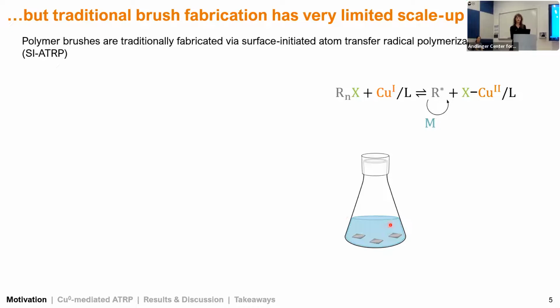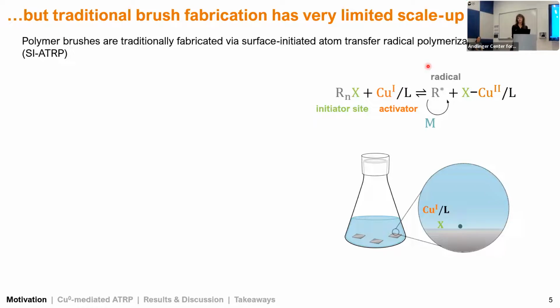So our substrates are functionalized with initiator sites. These are alkyl halide groups, and these react with an activator. This is typically a copper catalyst in the lower oxidation state to form radical sites, which react with monomers to form our growing polymer chains, and also producing a deactivator species, which is just our activator in the higher oxidation state. So for this to proceed, the environment has to be completely oxygen-free, and this is to prevent scavenging of our radicals as well as oxidation of our activator.